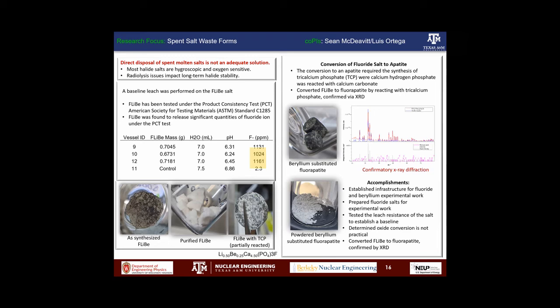So there are multiple waste form pathways that have been proposed, but in our case, we focus on the fluoride apatite, where FLIBE salt, we're using FLIBE salt, reacts with tricalcium phosphate. And you see some pictures of our salt. Bottom left, FLIBE as synthesized with impurities, once we purified the FLIBE, and then a pellet of FLIBE that has reacted with TCP, tricalcium phosphate.